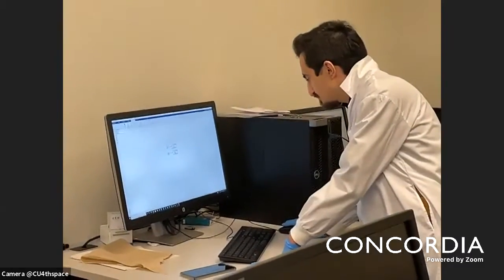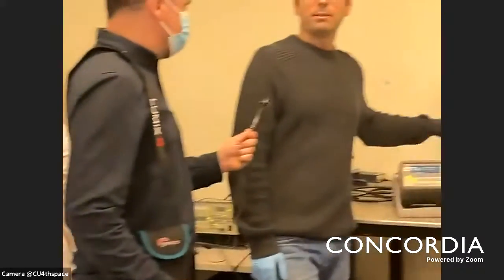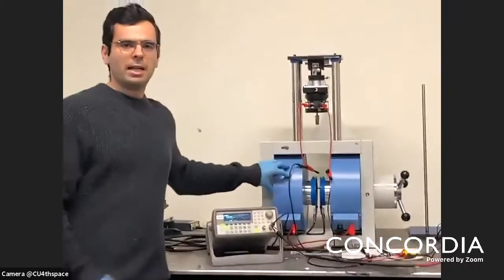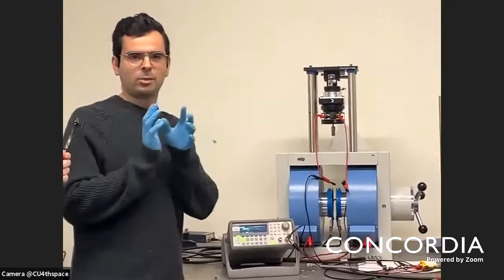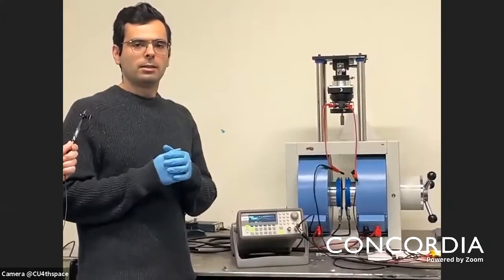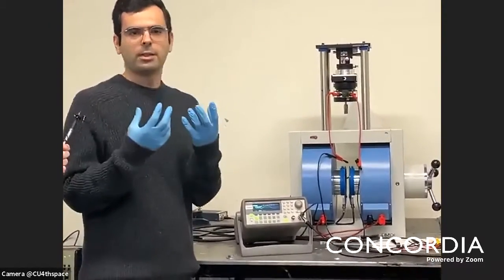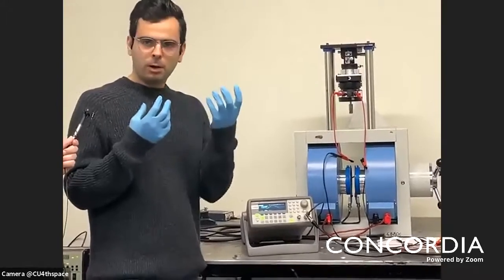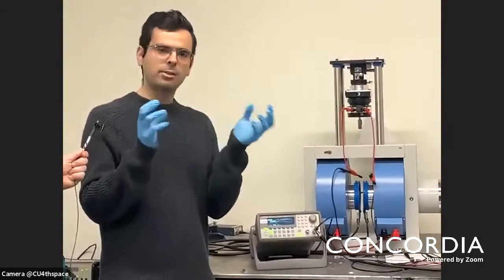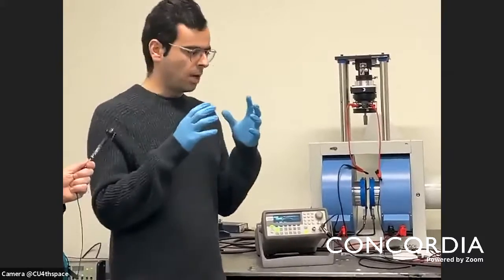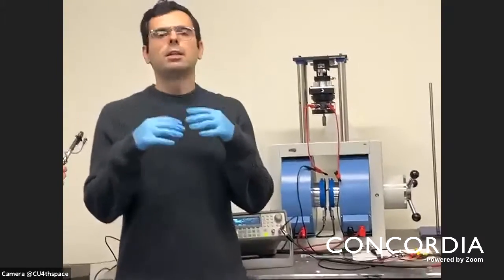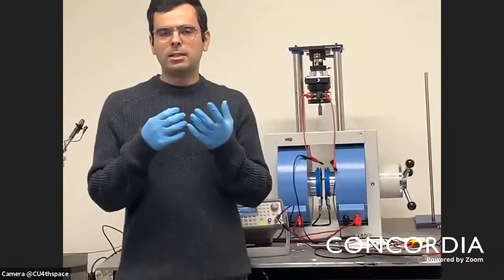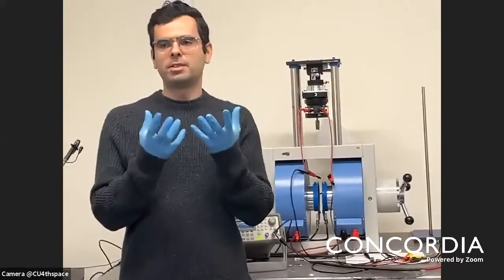So for this electromagnetic device, it can also be used for fabrication of MRE. Basically, MRE is magneto-rheological elastomers, MR elastomers, and for fabrication, all you have to do is mix iron powder with silicone. Mix them for about 5 minutes, and then degas the mixture. There's a device there I can show you.